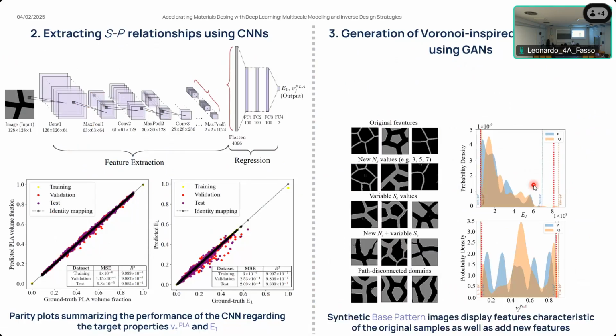Now, this is what I was mentioning before. Interestingly, these are all examples of images generated by the GAN after the training. For this set of images, we can see that they display the same features characterizing the original data, so it's able to reproduce the features associated with the original data it was trained on. However, it's also able to introduce many new features in other types of images, so it's able to extrapolate. For example, it's introducing a different number of cells, which were not part of the training set. It's also introducing a variable thickness of the grain boundaries, which is also not a characteristic that was used during the training. And it even reproduces some disconnected domains, which are also not present in the training data.